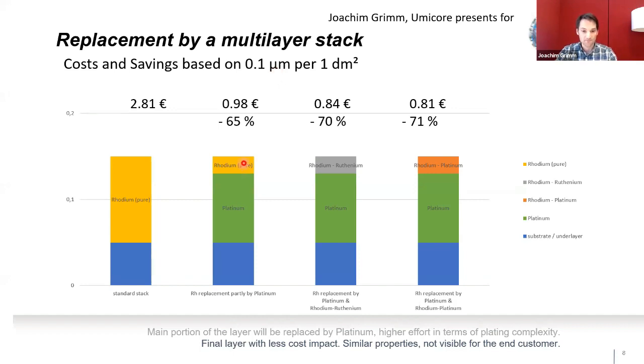The rhodium is on top, and the saving is a huge step to under €1 at the actual pricing, and it's about 65% of saving on this actual metal pricing. So this is a big step, having one additional plating underneath. So your sequence of your sterling silver as an example, a platinum layer on top, and then your pure white rhodium on top, giving you a huge saving.